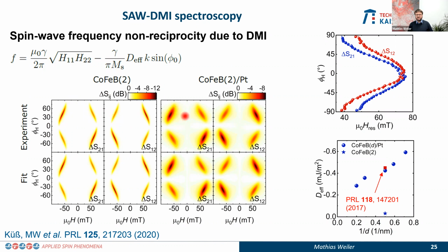And that changes if one additionally introduces the platinum, then you get also a shift of the resonance field. Okay? That can be quantitatively evaluated. From the shift of the resonance field, we can extract the effective or the volume average Dzyaloshinskii-Moriya interaction constant. And as you can see here, as you would expect, it scales as 1 over thickness of the ferromagnetic material, here the cobalt iron boron, because it's an interfacial effect coming from the platinum. And the absolute values agree well with those that have been previously published as a Dzyaloshinskii-Moriya constant for the cobalt iron boron platinum system. And of course, if you only look at bare cobalt iron boron, it's basically zero, what you observe here.